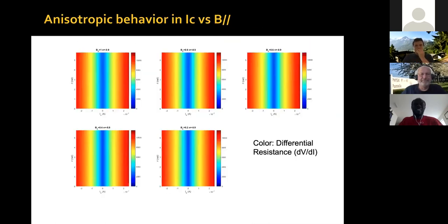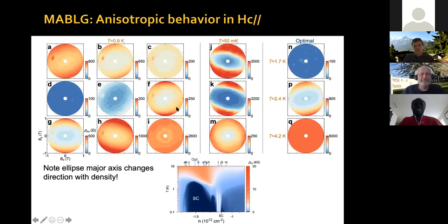So we also have measured. Here we're measuring the critical magnetic field, for which we take the system out of the superconducting state by a magnetic field, right? Can I ask you, in which direction is the current flowing? Yep. So we have measured this, and it is independent of the direction that the current flows. We have devices where we can flow the current along one direction or along the perpendicular direction, and the ellipse is always in the same direction at a particular doping. Okay.